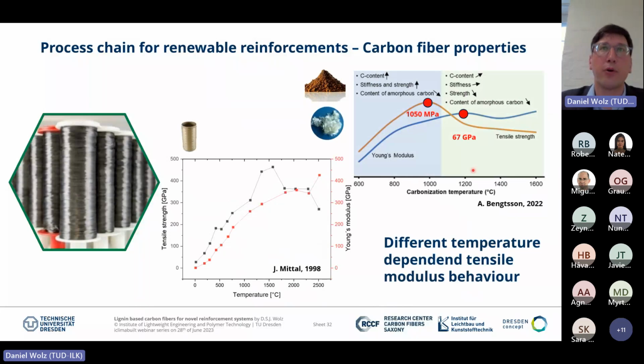Still, if we look at polyacrylonitrile precursor fibers, we see that we start with increasing temperatures and an increase in Young's modulus over the complete time. In the state of the art, this has not been proven for lignin and cellulose carbon fibers yet. So still there is a challenge: we can achieve here up to 500 gigapascal with polyacrylonitrile precursor fibers. The actual state of the art for lignin ones is 100. In this publication, it has been 67.